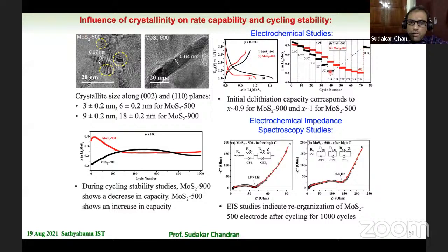500 is not good, but it is good in terms of cyclic stability, because initially it has very low lithium intake when measured at 10 C rate, and then slowly it picks up, which means, as you keep on cycling, its structural reorganization is happening, and therefore it makes more lithium take part in the electrochemical reaction. And of course, we did a very detailed study.